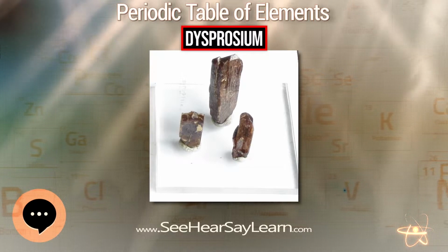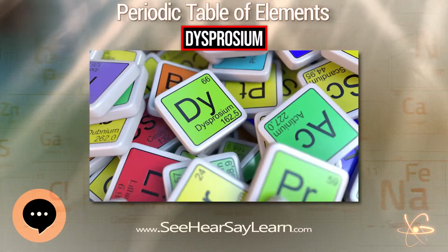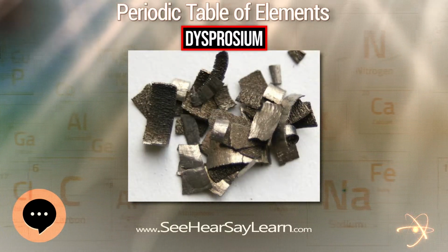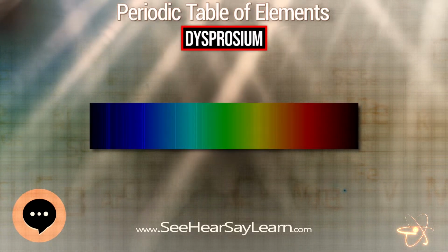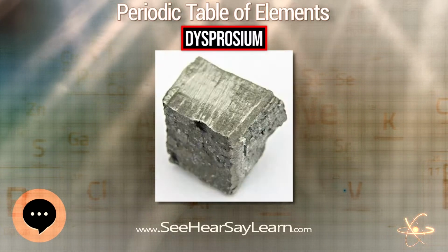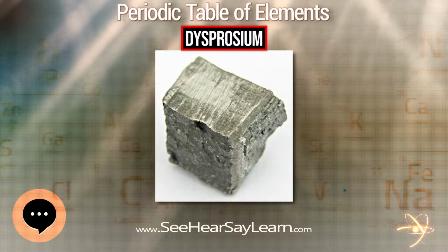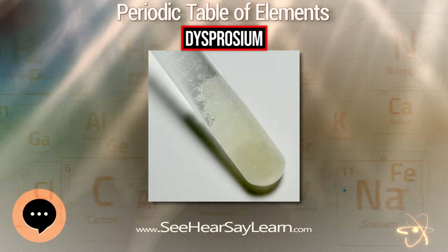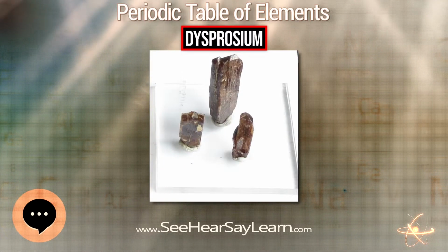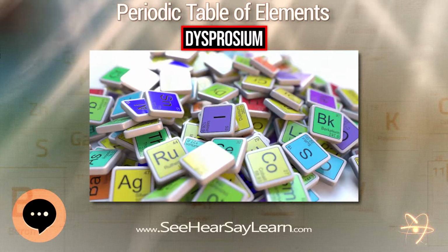The resulting dysprosium ions can then react with either fluorine or chlorine to form dysprosium fluoride, DyF3, or dysprosium chloride, DyCl3. These compounds can be reduced using either calcium or lithium metals in the following reactions. The components are placed in a tantalum crucible and fired in a helium atmosphere. As the reaction progresses, the resulting halide compounds and molten dysprosium separate due to differences in density. When the mixture cools, the dysprosium can be cut away from the impurities.